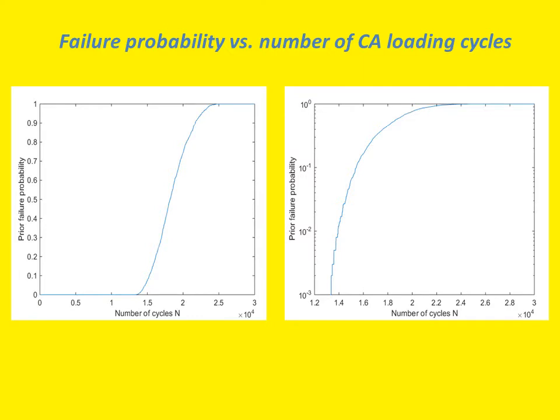These figures show the prior probability of fatigue failure as a function of n. It should be noted that this assessment is a so-called prior assessment. It is based on initial data on the material properties and general statistics on the performance of the structural component in similar conditions and does not account for information on actual performance of the component that can be obtained during technical inspections. As soon as we get data from non-destructive testing of the particular component during its operation, these prior assessments can be updated using Bayesian updating procedures.